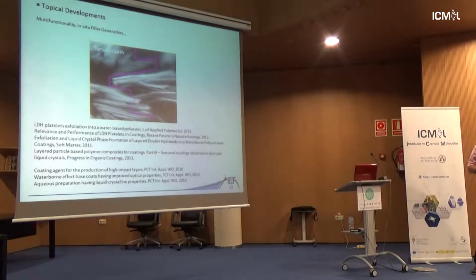Why is it of interest to use LDH? Because you have anisotropic platelets, so you have a very large form factor. It means that the lateral size is quite large, and the dimension between stacked layers is short. If you reach the single platelets, your form factor is quite big. It can be as big as 1,000. It's dimensionless, because you divide the lateral size by the thickness, and you get a number only.